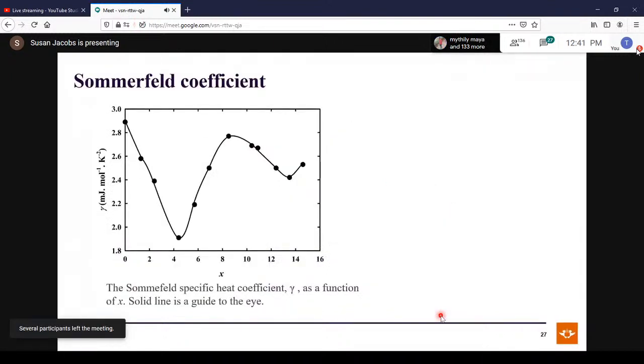Now, if you plot gamma that we got from specific heat as a function of concentration, once again, we see a deep minimum here, followed by an increase and a sharp decrease through the critical concentration, and hopefully it will flatten off. We need more samples to ensure that it is flattening off. Because we keep seeing this, we decided we need to investigate this further.